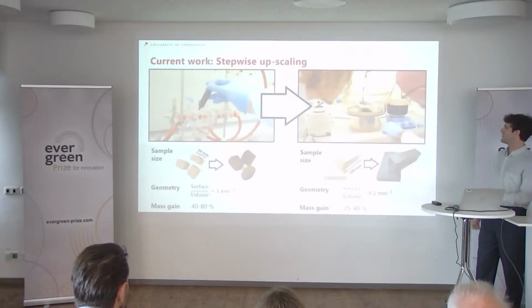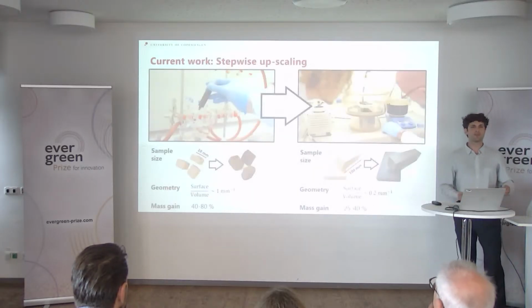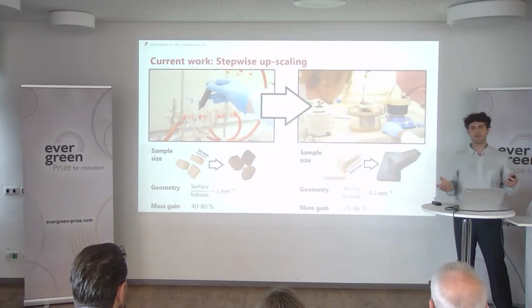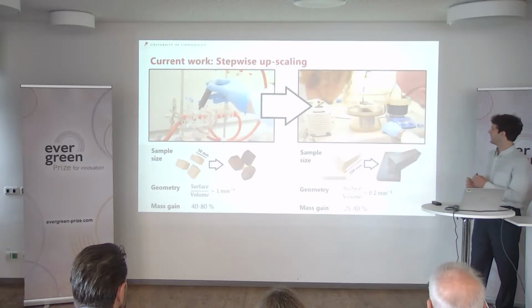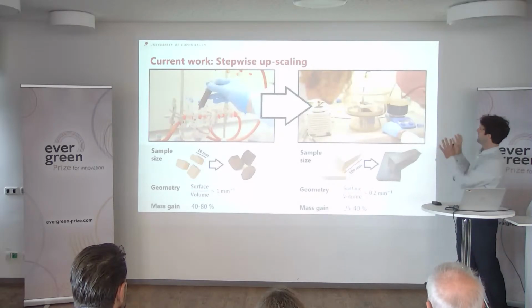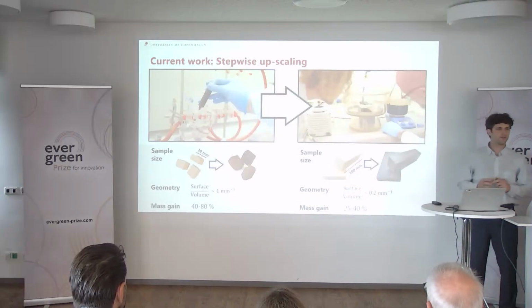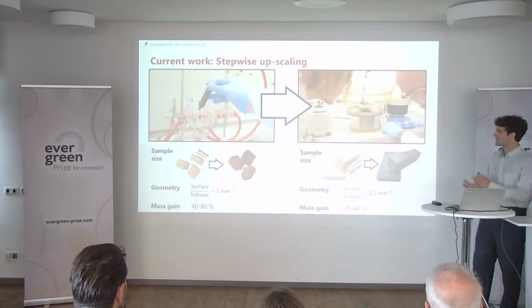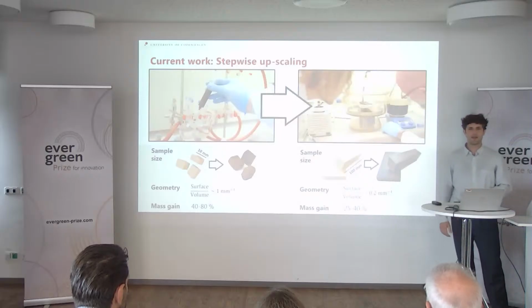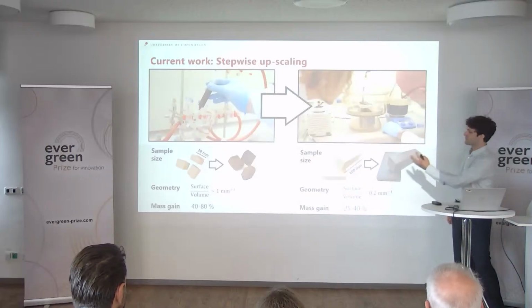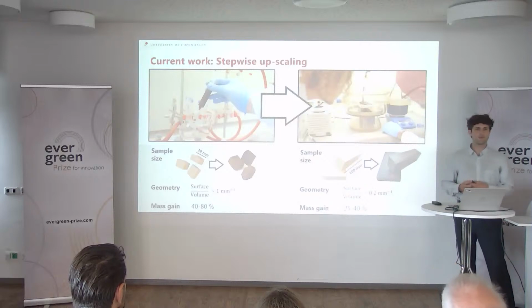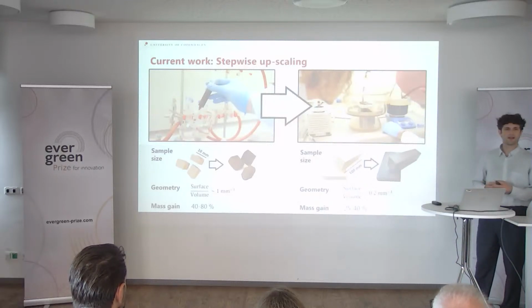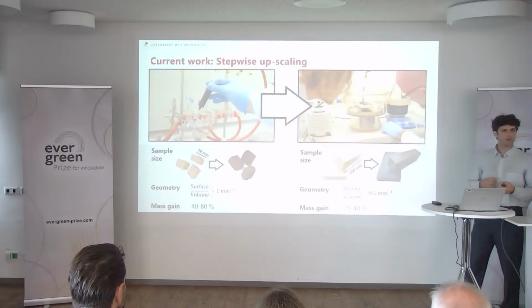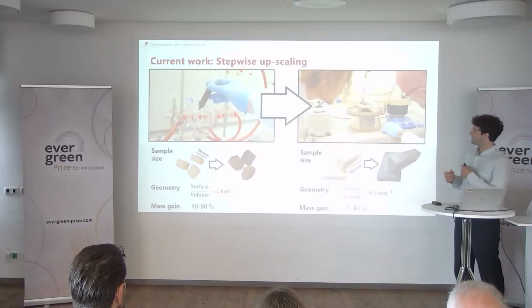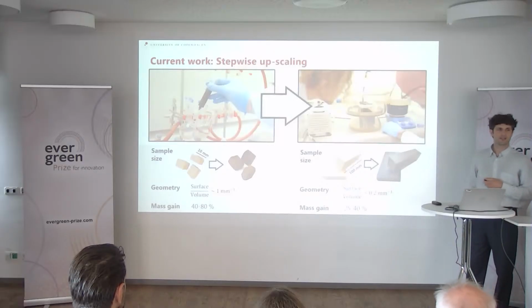We came back to the lab, and we were like, okay, now we need to improve this impregnation at larger scale, but we need a lab to do so. So we developed a larger vessel for impregnation of larger, longer samples. And this is what we're doing at the moment. Our aim is to reach the mass gain that we saw at small scale, and we're not too far from there. For example, with some samples, we even have higher mass gains than the smaller samples.